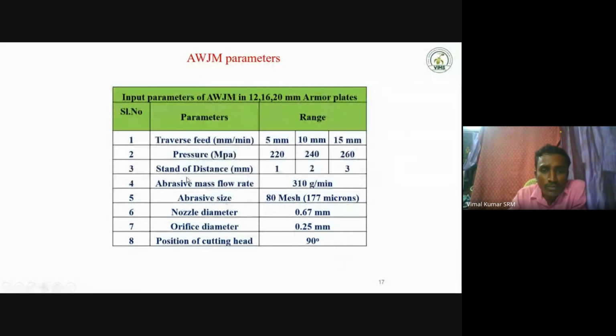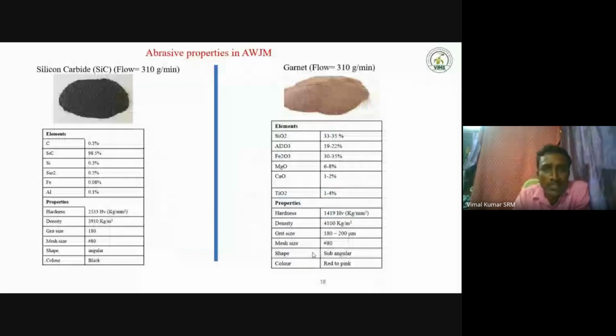So abrasive mass flow rate. Abrasive mass flow rate is 310 grams per minute. This is also a moderate value. And abrasive size: the size is garnet 80 mesh, 177 microns. The particle of the abrasives is also given by mesh size. The diameter is 0.67 mm. The orifice diameter, which also comes under the nozzle, is 0.25 mm. The position of cutting is 90 degrees. It's a vertical cutting. These are the initial parameters of the water jet machine.